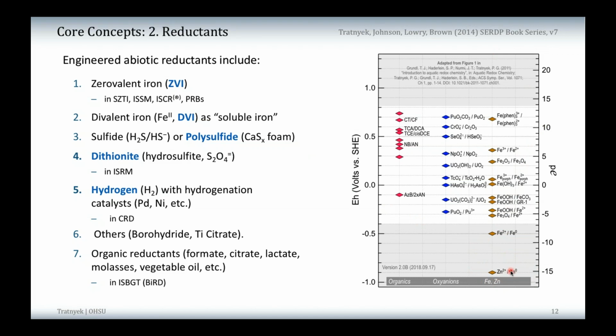You need to notice zero-valent zinc is a lot stronger reductant than iron, which in turn is a lot stronger than all of these intrinsic biogeochemical mineral phases. And also notice that all of these are pretty low on this ladder relative to these reducible organics and/or these reducible metal oxyanions. And so as a general rule, the thermodynamics are fairly favorable.